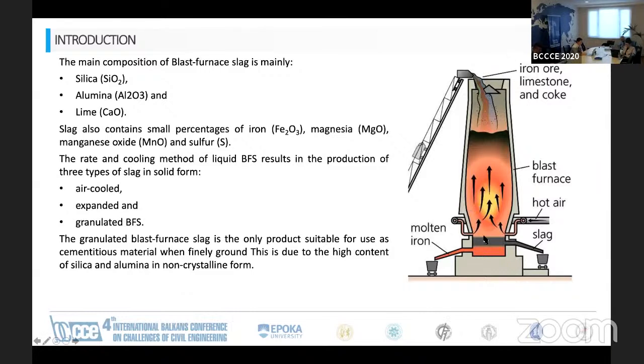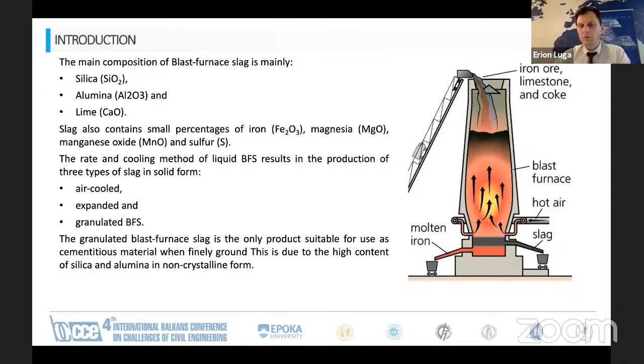And as you can see here, as iron is heavier, it comes down to the lower part, whereas slag is lighter. It stands in the upper part of this molten mass, and it is obtained from the right side, from the upper part. So these slags are byproducts. We do not produce slag purposely, but it comes out as a waste material from the production of iron.